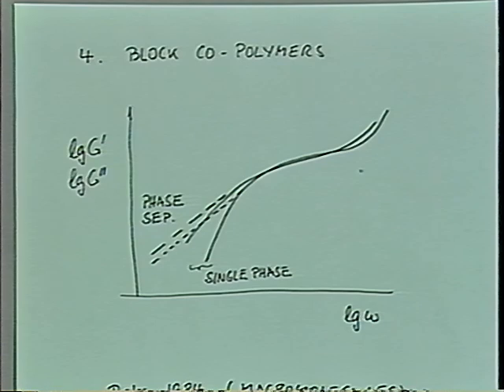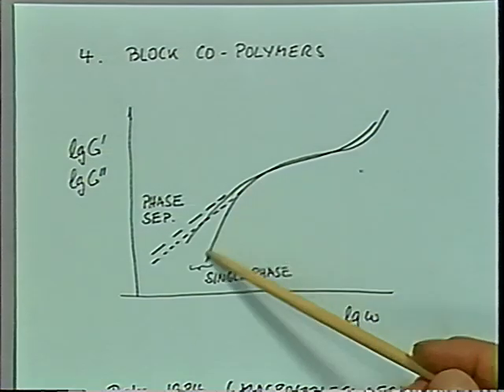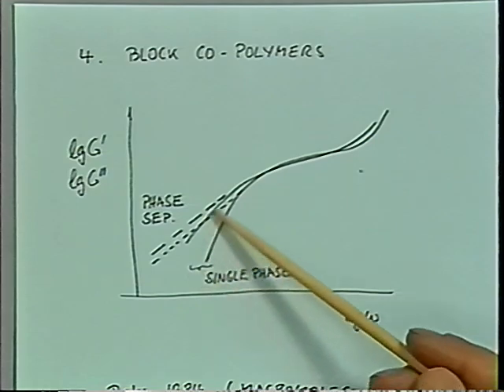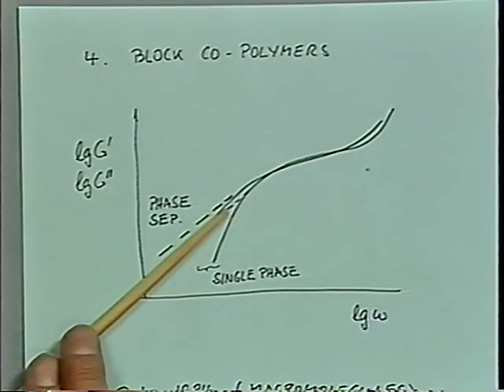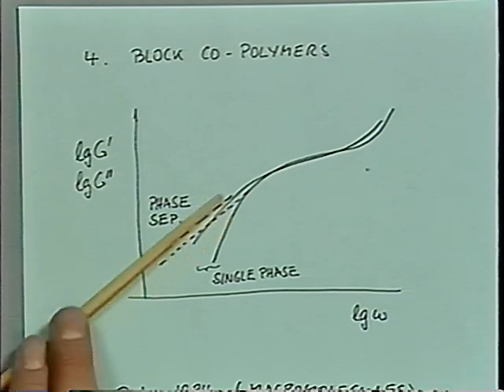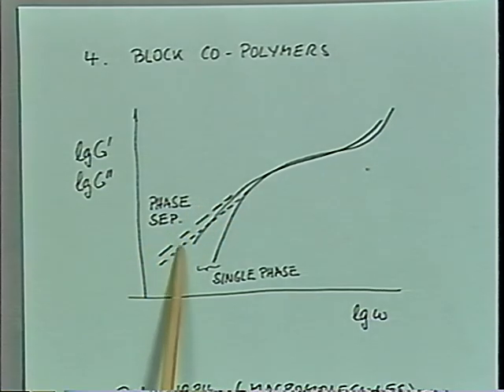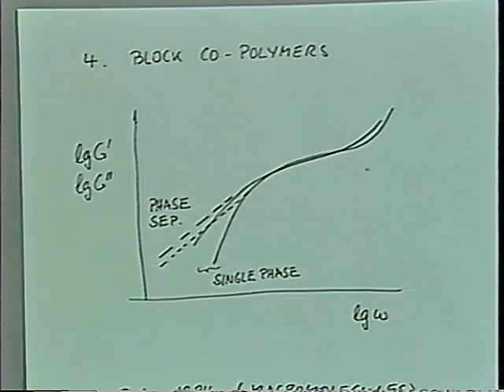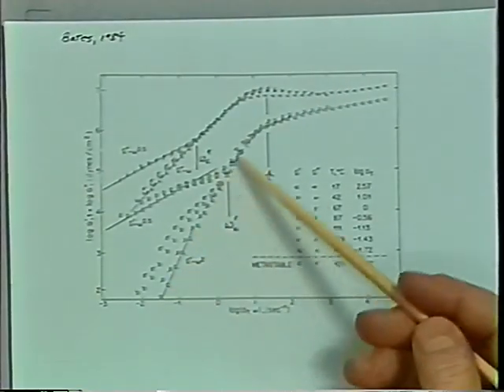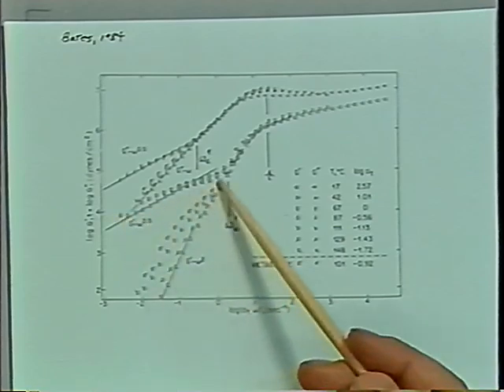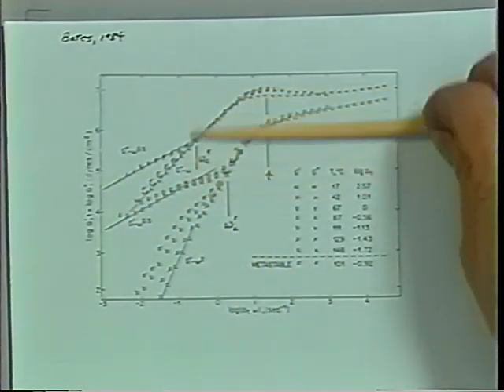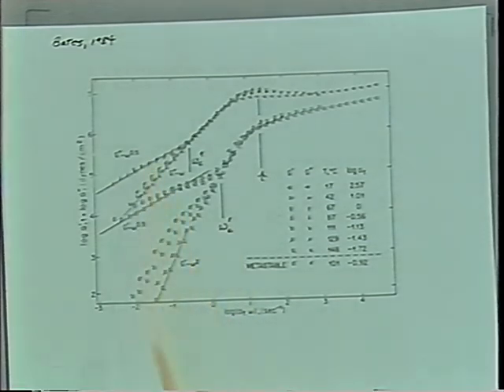Now the microphase separated structure causes some long-range connectivity in the material. So in the liquid state, one phase, the material is something like this. And as it goes into the phase-separated state, it has a power law region. In his case, it was a slope of 1/2, and then G prime is equal to G double prime. So that's a power law spectrum. And in fact, his original set of data looks like this. This is the original G prime, G double prime, and then at the gel point, both of them are shifted by 1 decade. Otherwise, this would be on top of that.